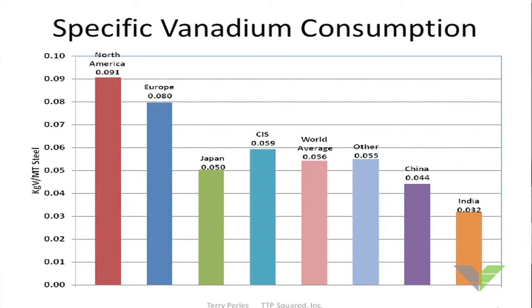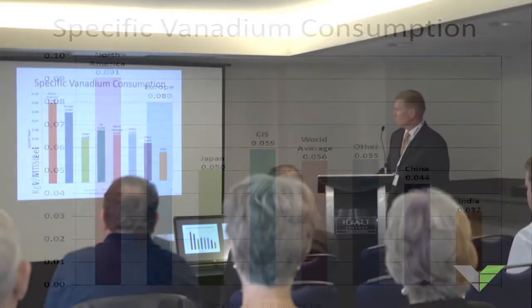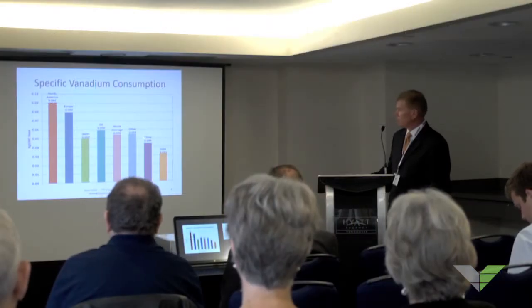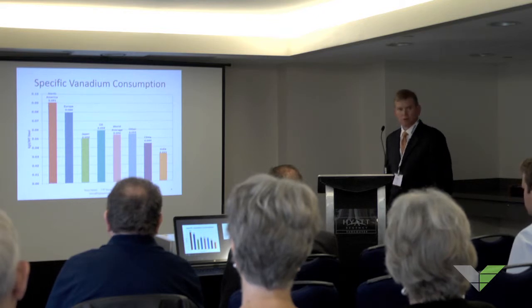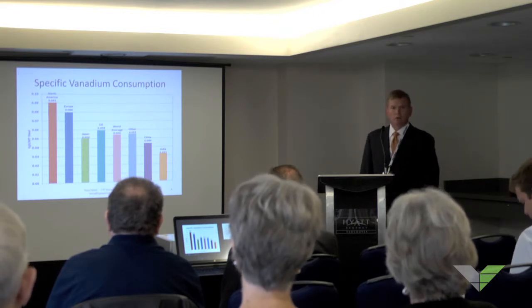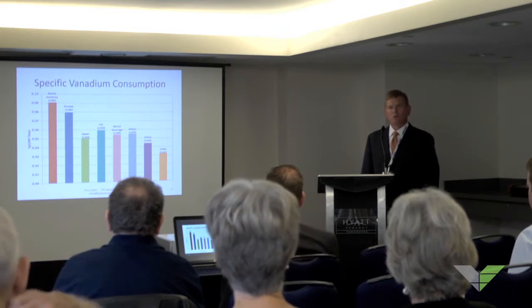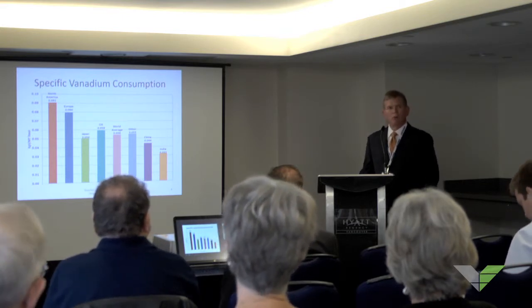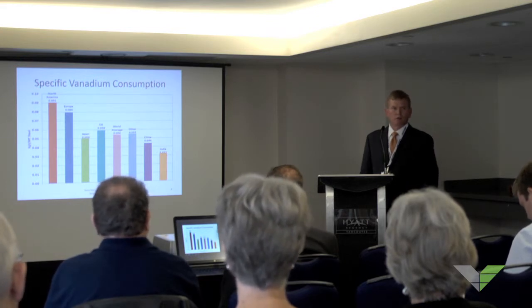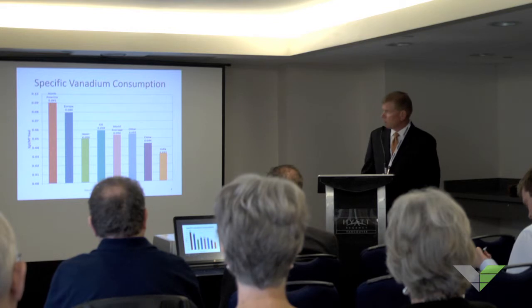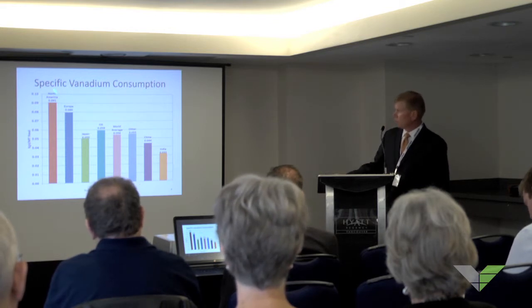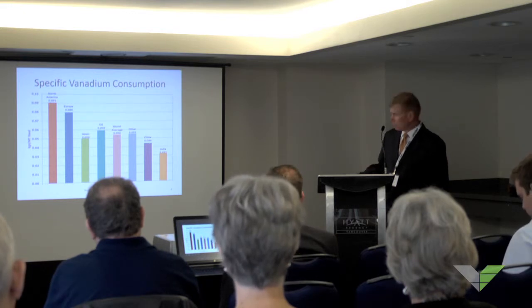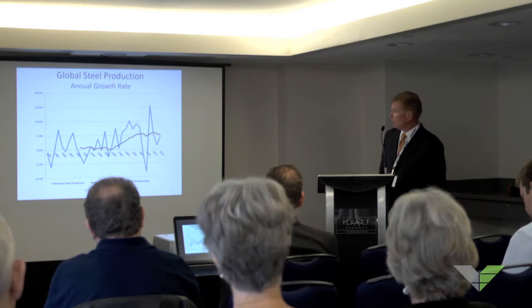So again, about 10 or 11% of the steel today contains vanadium, but there's plenty of space for that to move up. And interesting, you see the areas of the world where steel production is growing the fastest have the lowest specific consumption rate. This is typical as their industries mature and the knowledge and science improves in these areas. You see them moving more quickly to adopt higher strength steels and consume more vanadium. So what's happening is across the board, all these specific consumption rates are going up, but these ones are moving up much quicker, and that really has some strong implications for the demand of vanadium.